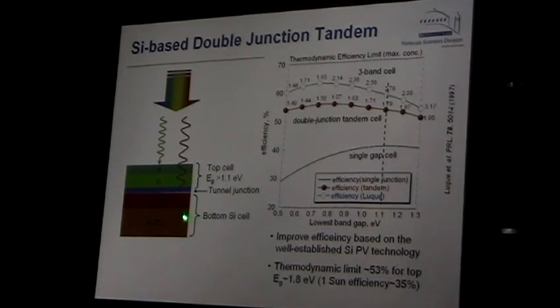And in this case, of course, I mentioned to you that one of our tandems we are working on is just silicon, PN junction, and gallium indium nitride on the top. This was our objective. But in fact, if you take silicon and add any material with a gap of about 1.7 or 1.8 electron volt, you would produce a very good tandem with very good efficiency.